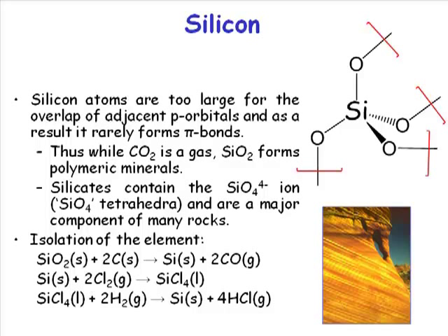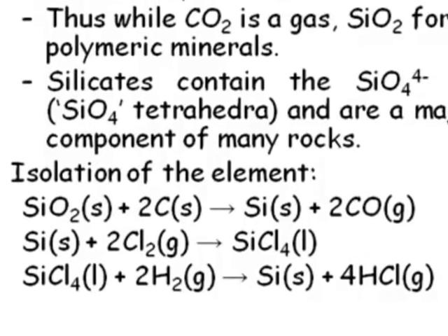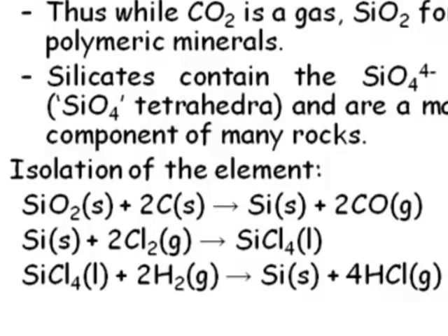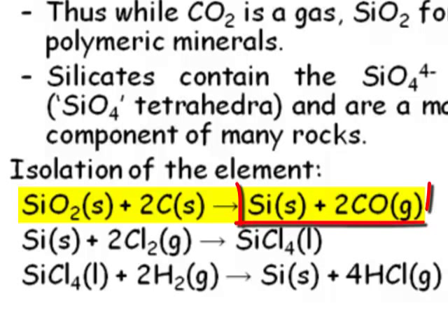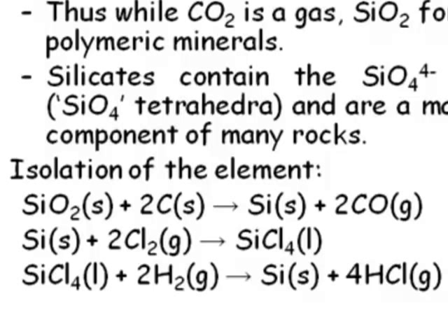In order to be able to grow very large single crystals of silicon, you have to have very high purity silicon. How do you ensure that your silicon is very pure? You can make silicon fairly easily. If you take sand and you heat it with carbon in the form of coke to very high temperatures, then you can isolate elemental silicon and you get carbon monoxide coming off. The problem with that method is that silica, sand, cannot be purified. You can't recrystallize this material very easily at all.